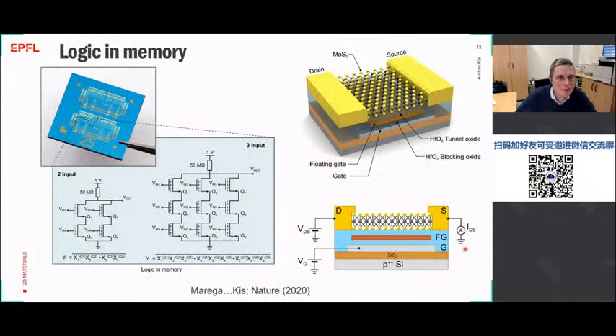So one example where we recently used this material was in a paper we just published in Nature a couple of weeks ago, where we showed that, starting off with these large-scale MOCVD grown MoS2, we could realize floating gate field effect transistors, which work in a similar way as the flash memories in our cell phones and consumer electronics. Here we have a floating gate in which, depending on the voltage configuration, we can store or remove charges from it. And when you have the presence of these charges in the floating gate, it can influence the conductivity of your transistor.